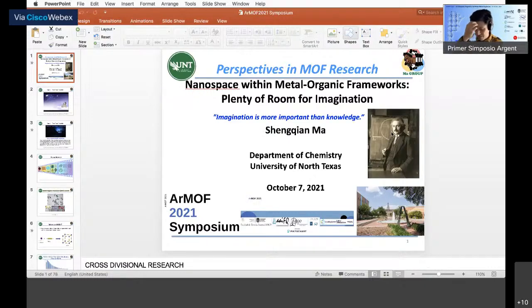I noticed that when you presented the approach to CO2 capture using polymer-in-MOFs, and then showed how using a cage-type MOF like MIL-101 chromium or a channel MOF like PCN gives some difference in activity, my question is this: if you have a host polymer within the MOF porosity, it's natural that you would lose some of the surface area of the naked MOF. And since the application of this reaction, or other reactions you use, is not in gas phase but liquid phase, how relevant is it, for a liquid phase application such as separation or liquid phase catalysis, to have a well-activated MOF prior to the experiment?